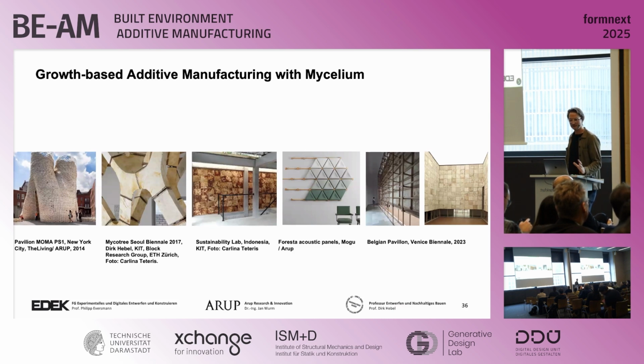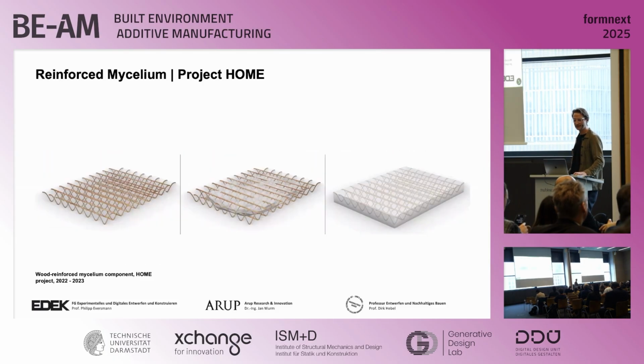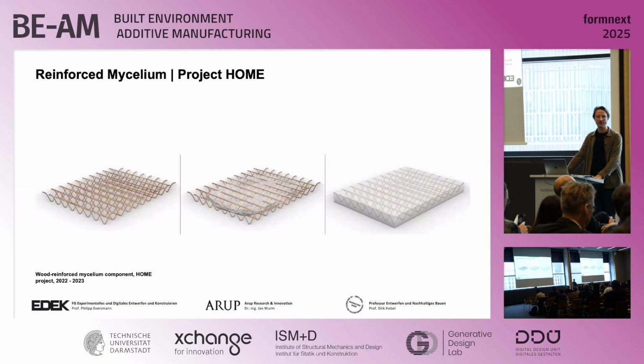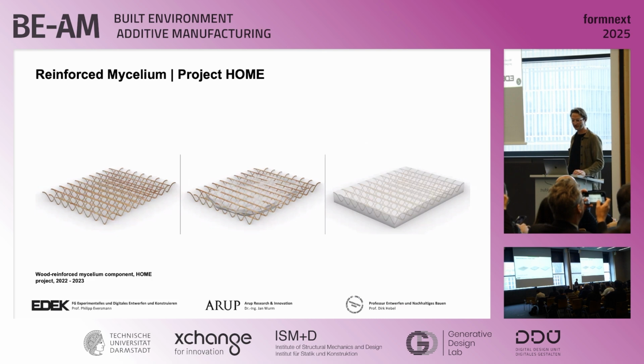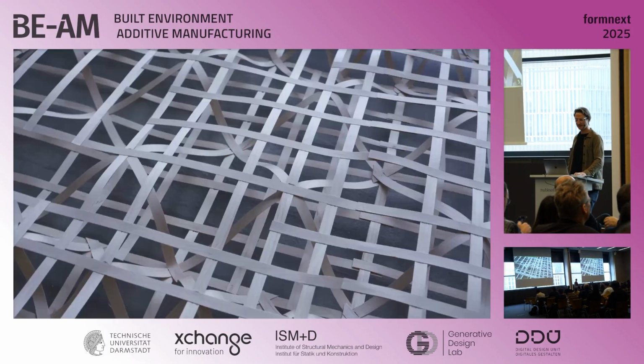It has really good acoustic and insulating properties, similar to EPS foams, so not very strong. It has been used for lots of exhibition structures, but with very small elements and short spans, so very limited structural capacity. That was the idea of the research: to combine two materials, a bit like reinforced concrete, and create a reinforced mycelium through these 3D lattices. And you can see that here.